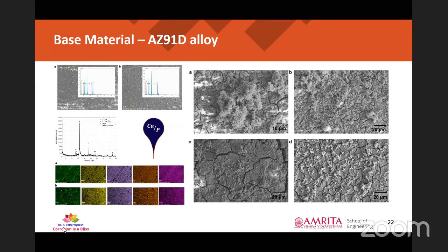Why I'm speaking about this calcium to phosphorus ratio is that this ratio will give us an idea whether hydroxyapatite precipitates over the surface after immersion or not. Why? Because hydroxyapatite is a mimic of the bone material. So if this hydroxyapatite completely forms over the surface, it will enhance osteoconductivity too. So we can conclude that since there is precipitation of hydroxyapatite based crystals over the surface, the magnesium alloy is deemed to be osteoconductive and biocompatible too.